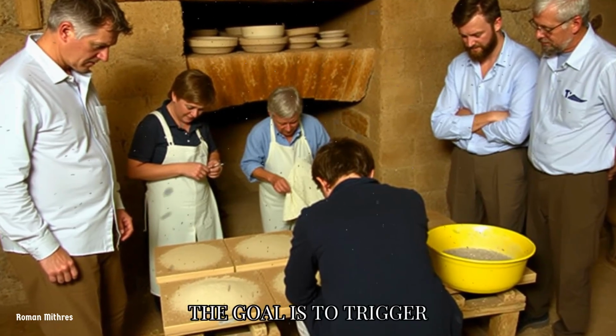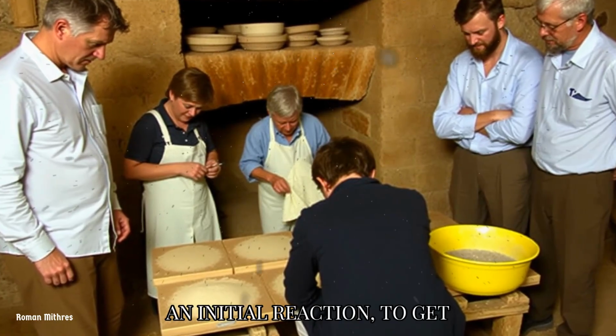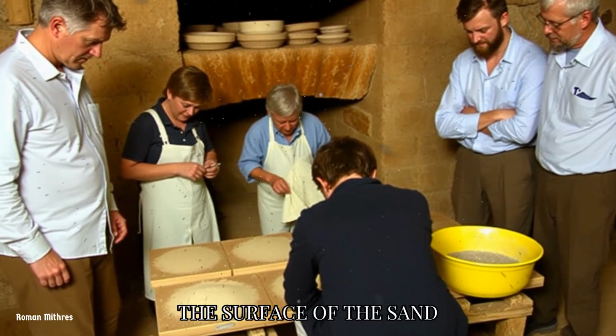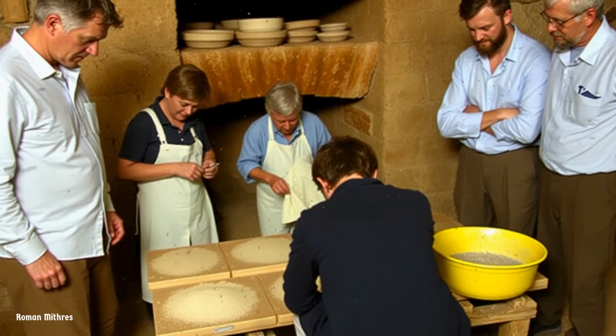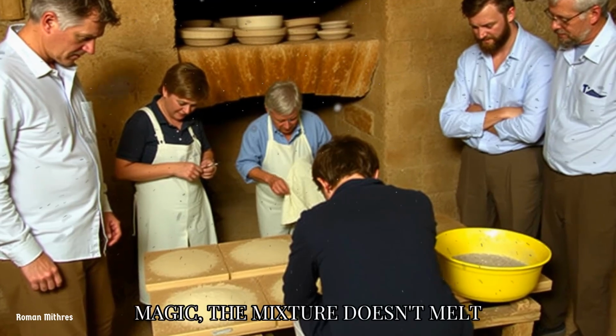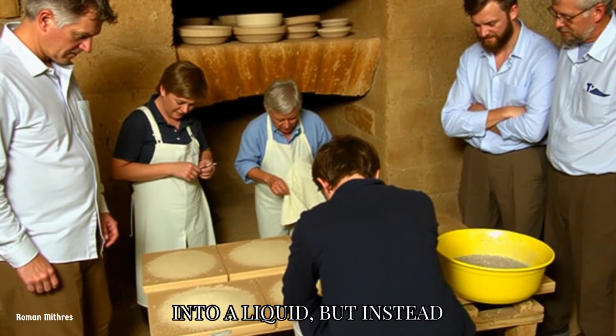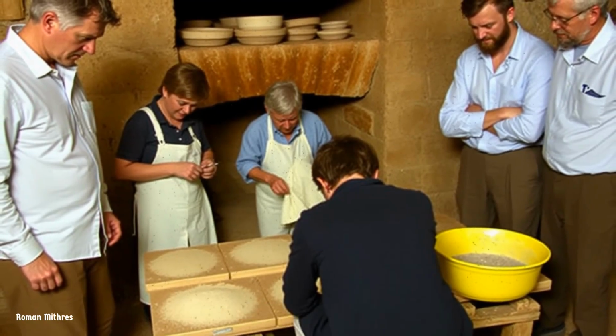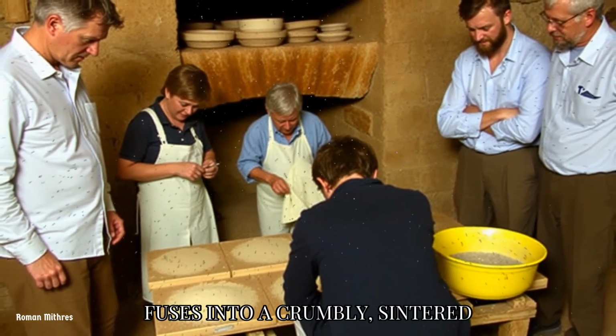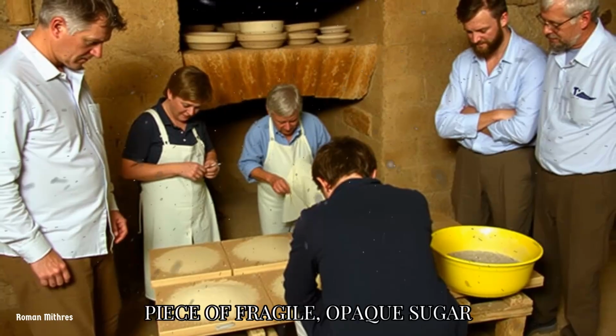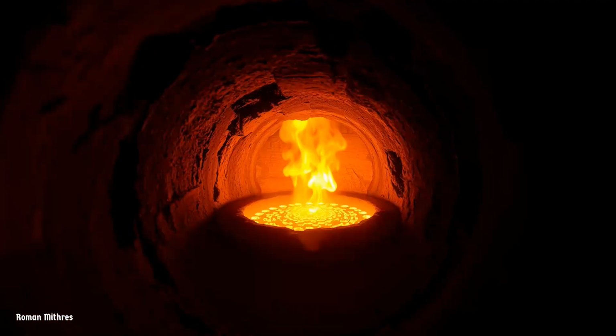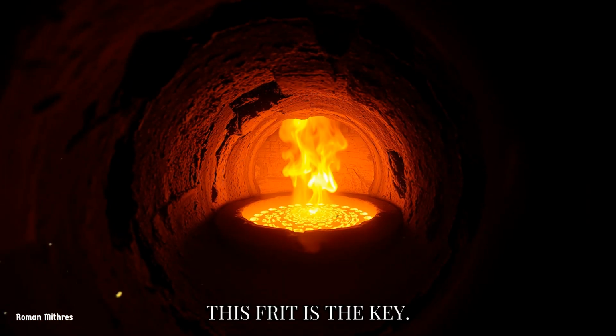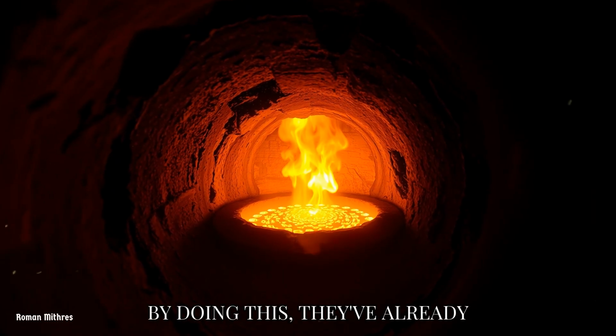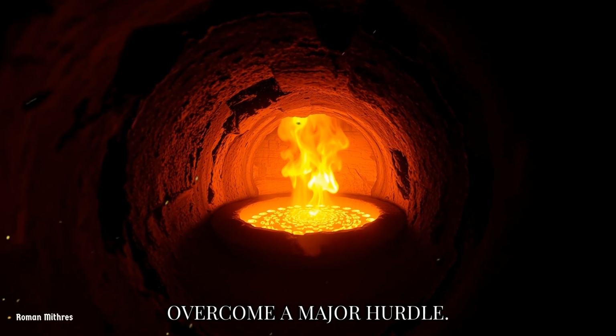The goal is to trigger an initial reaction, to get the soda to begin dissolving the surface of the sand grain. As the heat works its magic, the mixture doesn't melt into a liquid, but instead fuses into a crumbly, sintered cake that looks like a piece of fragile, opaque sugar glass. This frit is the key. By doing this, they've already overcome a major hurdle.